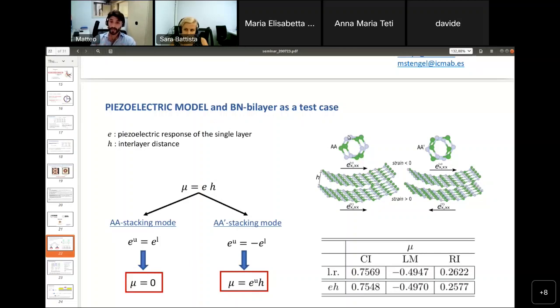but responding by linearity in an opposite way. So since they respond in an opposite way, if we stack them in the same direction, the overall effect is 0. Whereas if we stack them in opposite directions, the two singular responses sum, and the overall effect is non-zero. So actually, the symmetry of the piezoelectric tensor is compatible with the symmetry of, in this case, the single layer. So piezoelectricity is very important to the overall effect in this case.